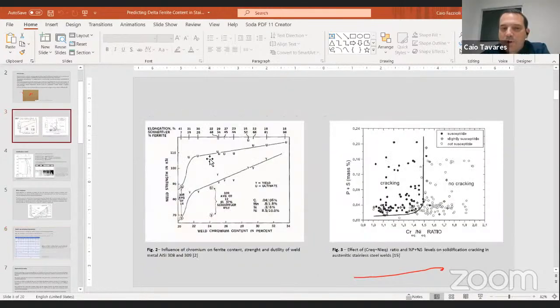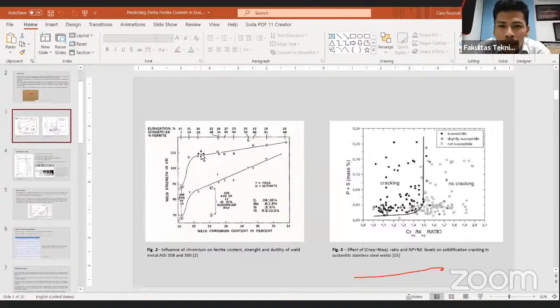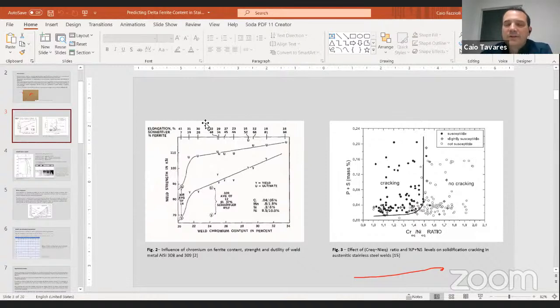Yes, the tendency is to increase the mechanical properties, but reduce a little bit the resistance to corrosion. So we need to be careful when we play with delta ferrite in stainless steel, so as not to compromise the corrosion resistance of the alloy. And usually, what is the typical corrosion? Is it pitting corrosion? Usually it's pitting corrosion. I'm not a real expert in this subject, but I would say it's pitting corrosion.